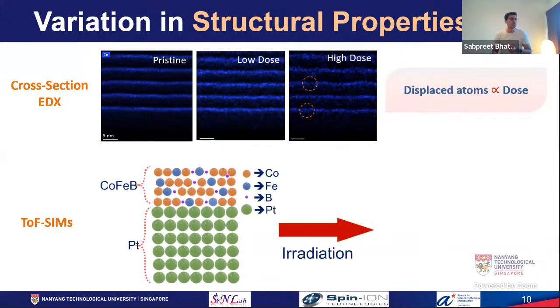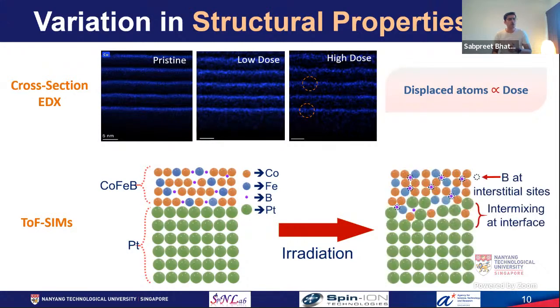But in conclusion, the structural properties vary. After irradiation, we were able to see the intermixing of atoms at the interface. Moreover, atoms like boron are migrating between the ferromagnetic atoms, at the interstitial sites of the cobalt and iron. Now, this change in the intermixing of the interface will cause a change in the interfacial properties, whereas the migration of the boron will cause a change in the bulk properties like saturation magnetization and exchange energy.